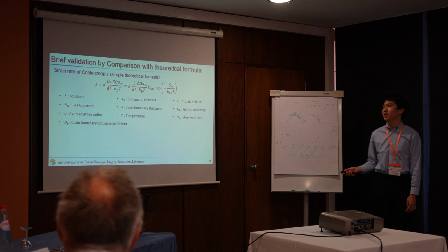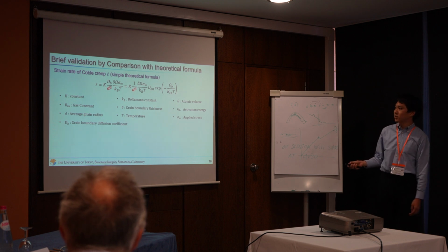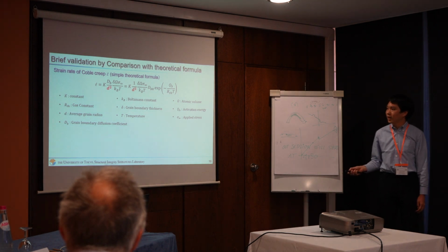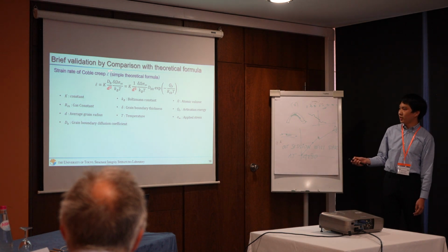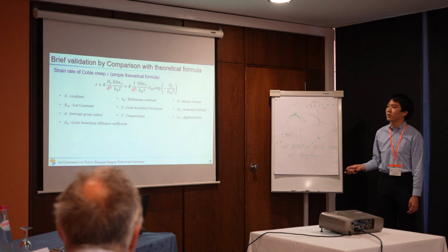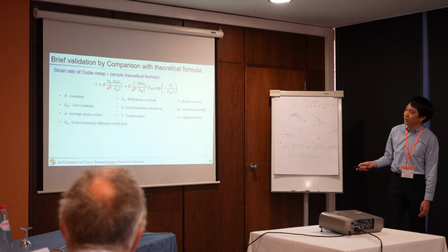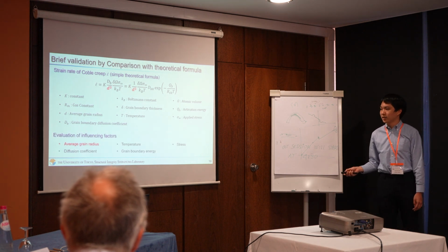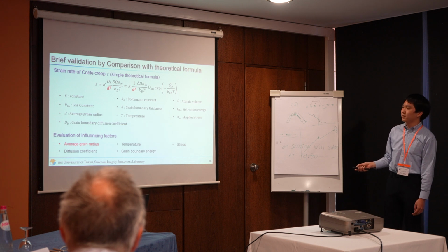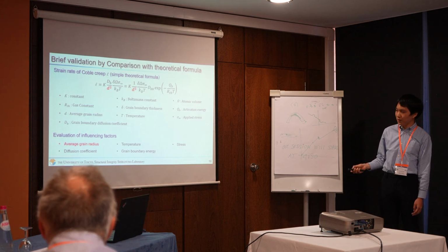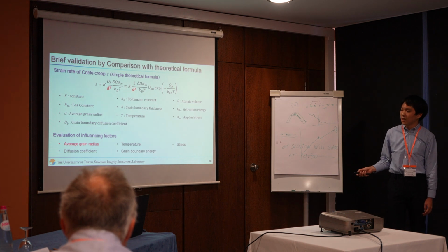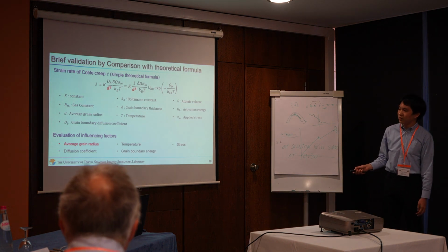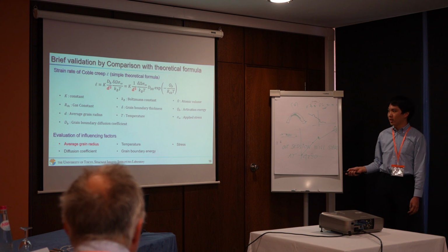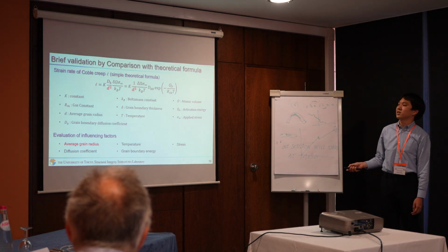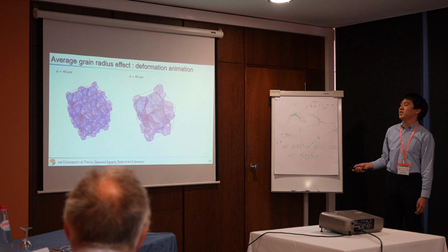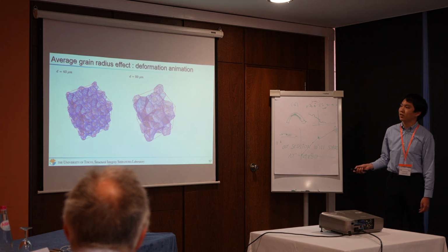And next, I did a brief validation by comparison with the theoretical formula. And this is the theoretical formula of the strain rate of Coble creep. In this theoretical formula, the influencing factors are average grain radius, temperature, stress, diffusion coefficient, and grain boundary energy. And changing these influencing factors, we calculated some patterns. And these are examples of changing the grain radius.